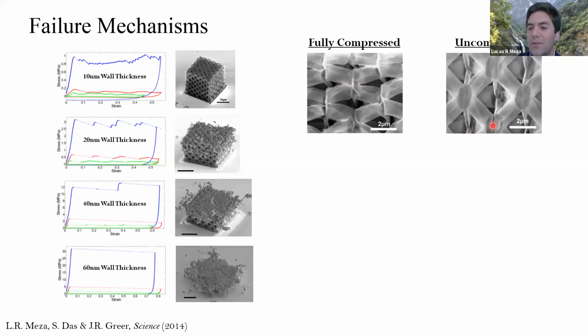After we unload, we do see cracks form. There's some cracking that exists, which is why we don't see full recovery. But globally, the node remains intact, so the structure is able to recover. And there's no plasticity mechanisms because it's a brittle material — it's either broken or it's not broken. If it's not broken, it's able to bounce back, although it loses some of its integrity.